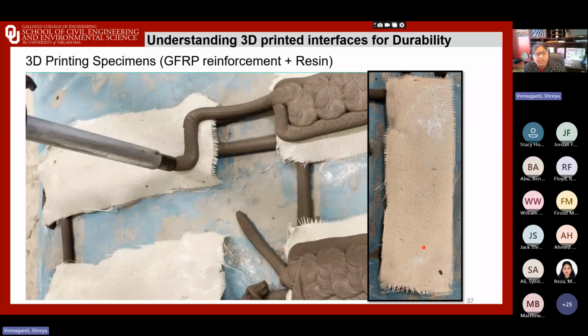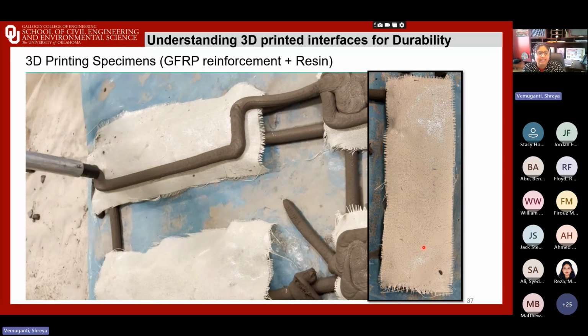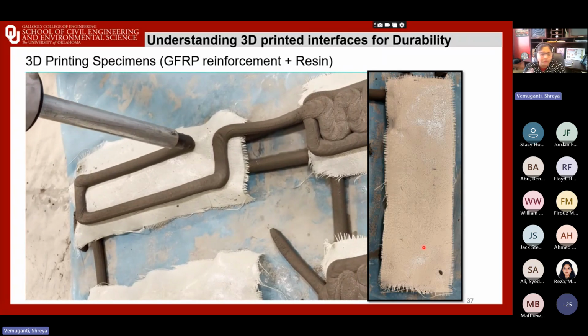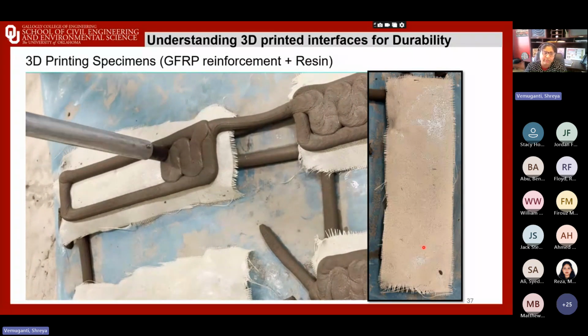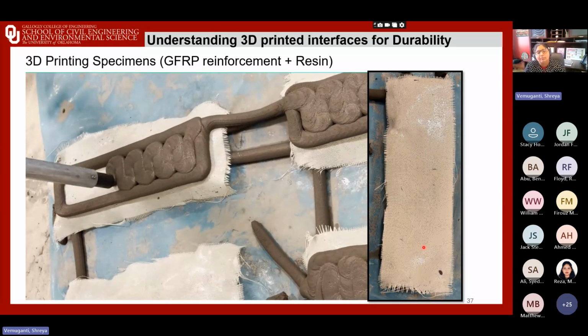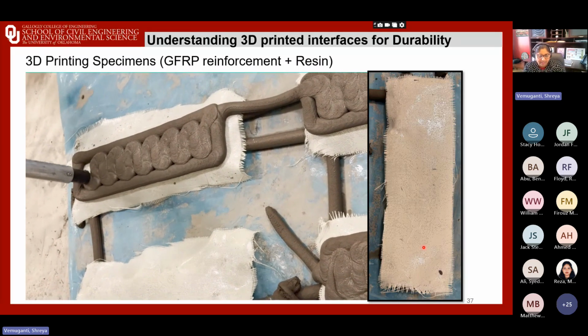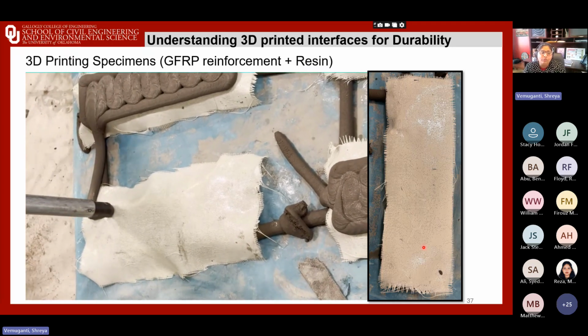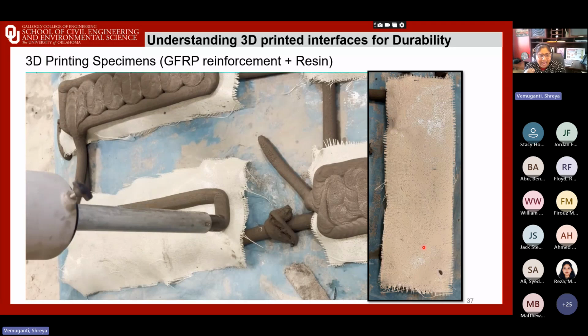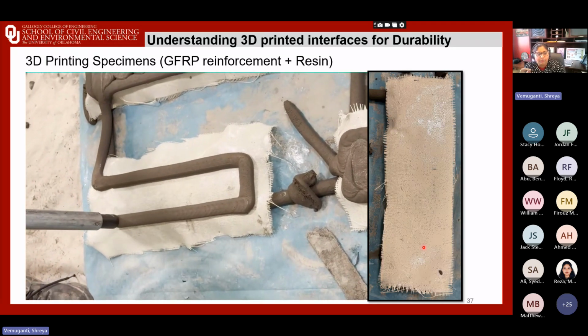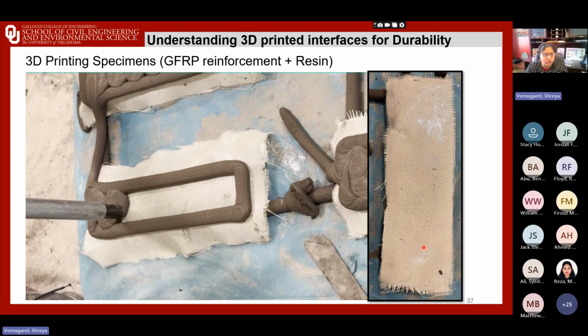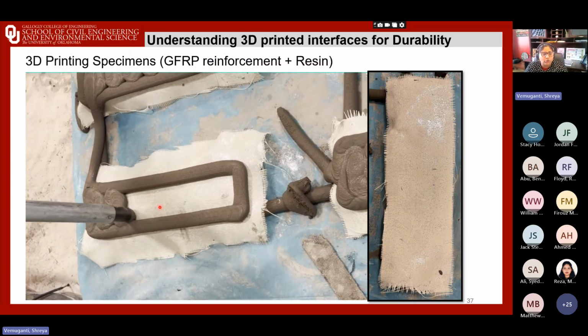In this particular video, you see the same GFRP reinforcement, but what we did is we saturated it in resin. So it's not a wet layup on the printed specimen itself, but it's a pre-saturation that we did, removing any excess resin that is already pre-mixed with hardener. And then we've placed these fabrics on top of the beams at those design interfaces and printed the next layer on. So you can clearly see how this fabric is laid. Of course, we had to ensure there is more fabric than needed because we didn't want the fabric to fall off during printing because the nozzle is moving and has this vibration effect.